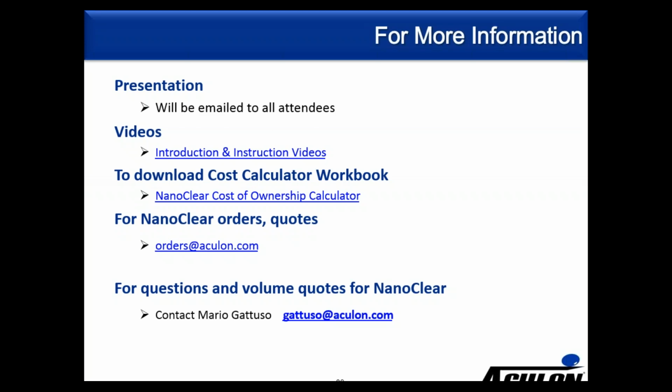The next question is, how long does NanoClear last? Okay, that's a great question as well, and the lifetime of NanoClear is certainly relative to how long NanoClear is utilized. So as long as you are using a soft under stencil wipe, you're using a pH neutral cleaner, then the NanoClear will not be damaged and will last a very significant amount of time. So we find that users who are using recommended practices will see that they get 25,000 to 50,000 prints out of the NanoClear.